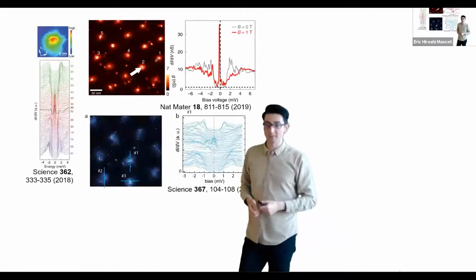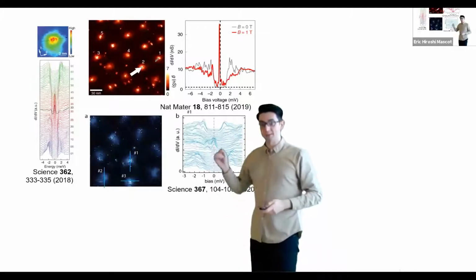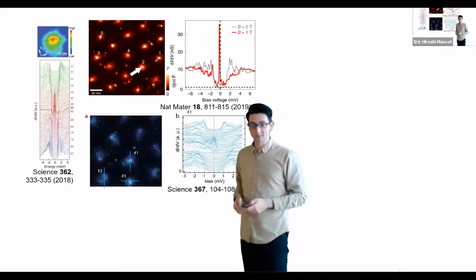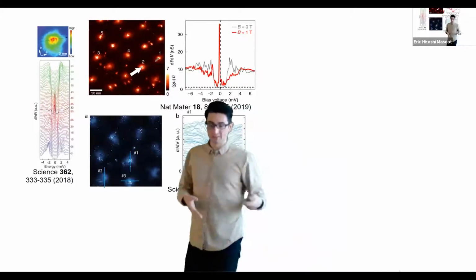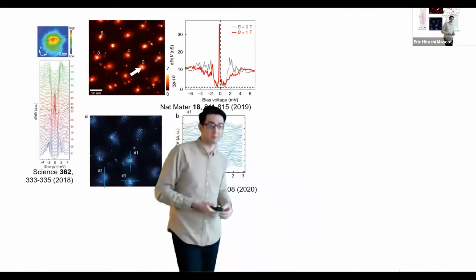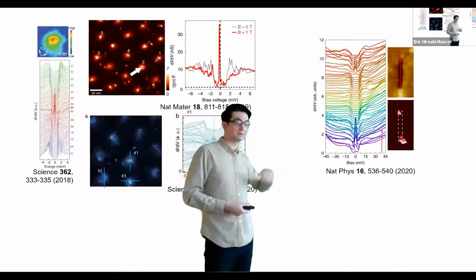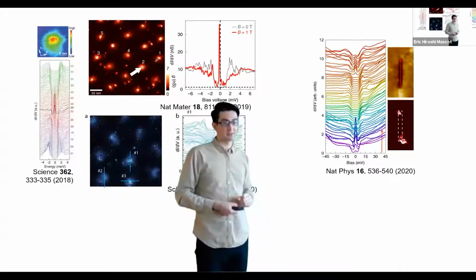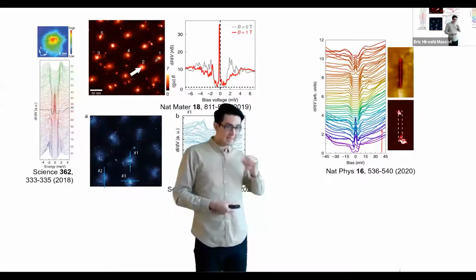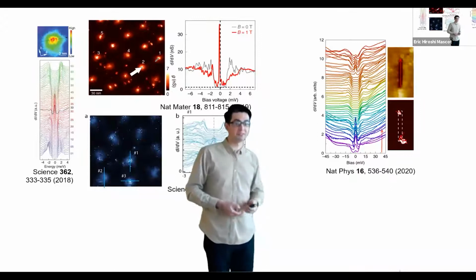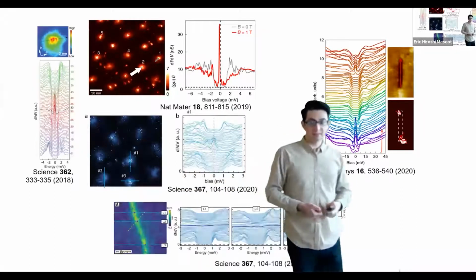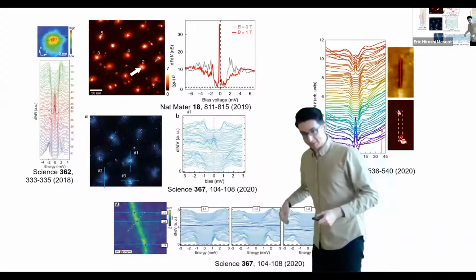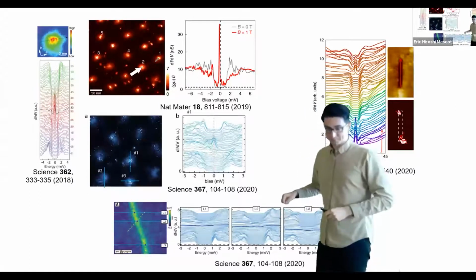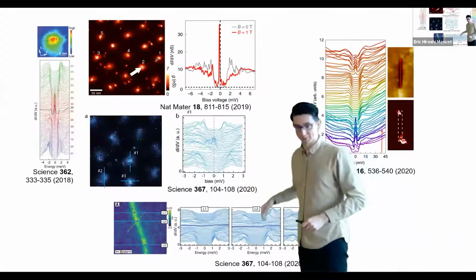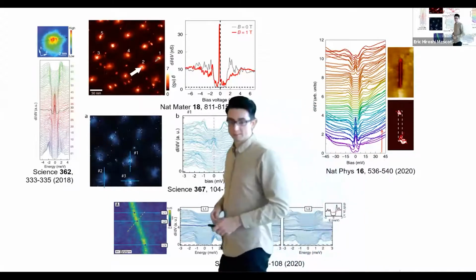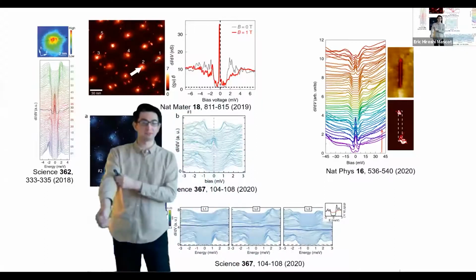So these experiments found zero energy states in the cores of vortices, which is a signature that you would expect from a Majorana bound state. Here, there's a line defect in the surface of FeSeTe, and at the ends of the chain, they find zero energy states. And in this experiment, at a domain wall, they see an edge state that crosses the superconducting gap, which you would expect from a chiral Majorana edge mode.